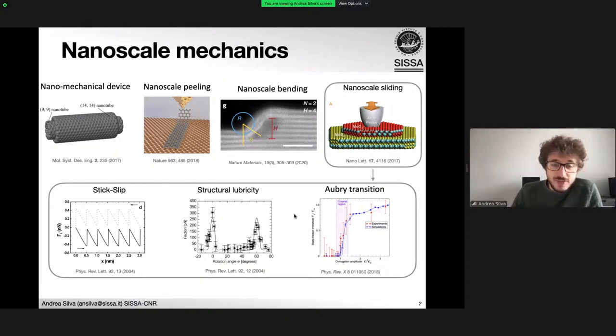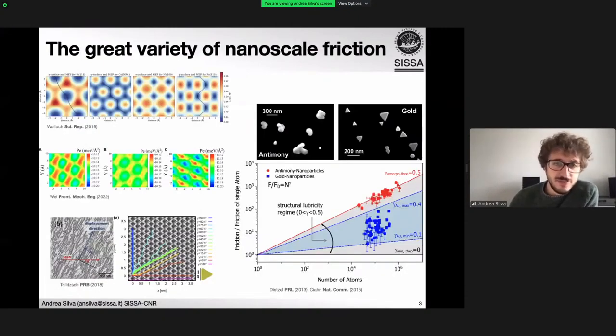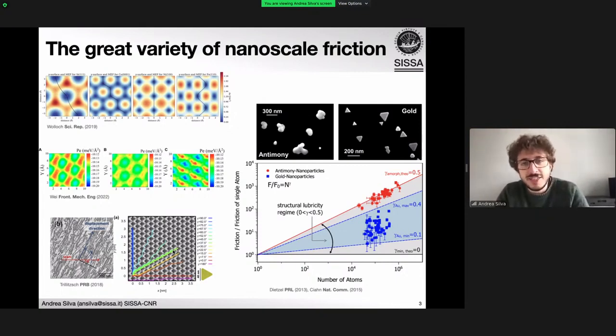These two behaviors are linked by something called the Aubry transition that can also mix one with the other. And all this nanoscale sliding is sort of controlled by the moire pattern that develops at the crystal-crystal interface. The zoology and the variety of these patterns and specific crystal interfaces is very big, as we saw in the talks on Monday. So it can be probed by high throughput density functional studies, where you can compute the potential energy surface of two crystalline interfaces sliding. It has also been probed in experiments where, for example, in the case of molybdenum disulfide island sliding on gold, the system is pushed always in the same direction, but it goes along a preferential direction due to the crystal symmetry. So there is some directional locking of the motion. And at this small scale, the effect of finite size is also very important, as was shown in 2013 by Dietzel.